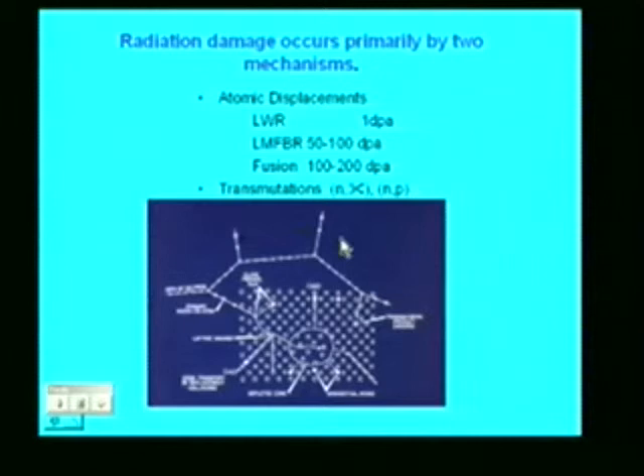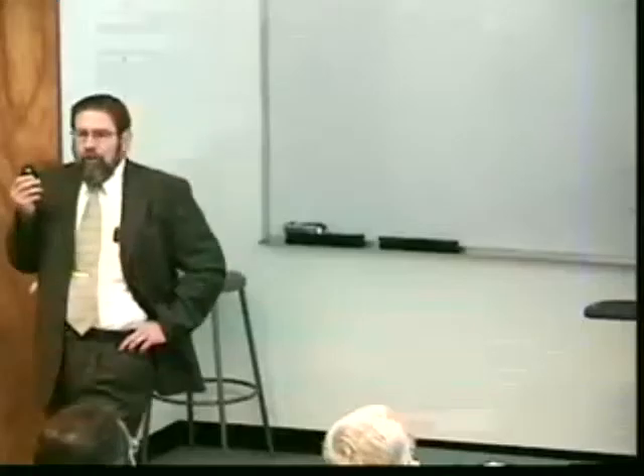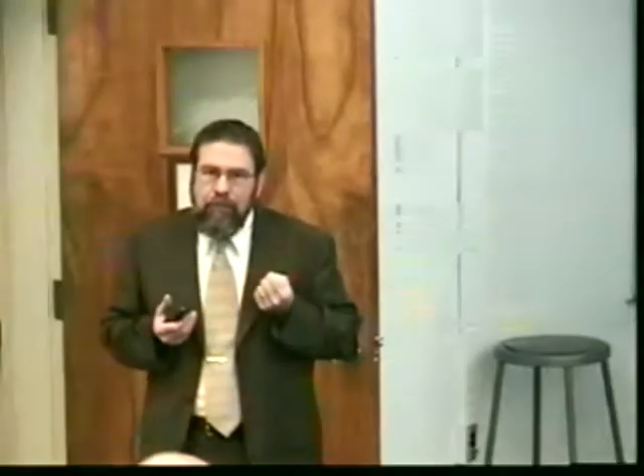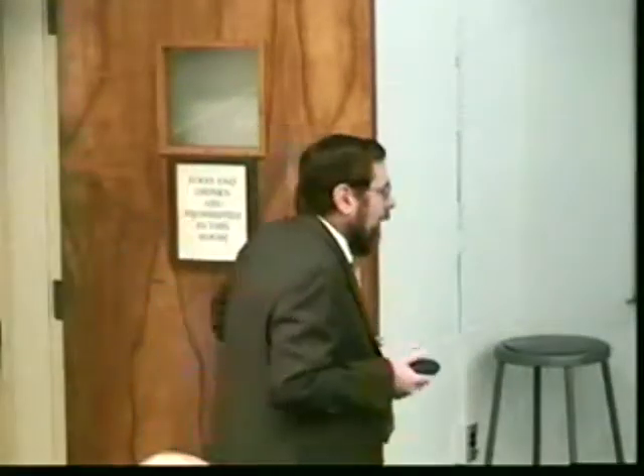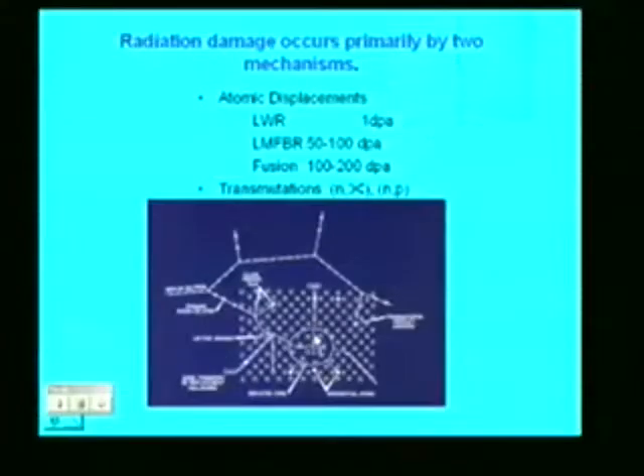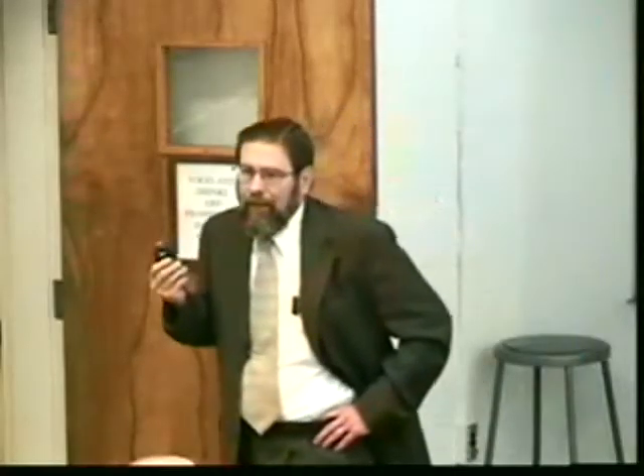So we get a cascading effect, and we said that they eject atoms from the lattice, so they produce an atom that's not in a lattice site, called an interstitial, squeezed in between, and where that atom came from is a vacancy. And at the core of that cascade, this diagram is showing we have something rich in vacancies, and then the interstitials usually are farther away. Just to put things in perspective, in an LWR, the materials may see about one displacement per atom. So that in a lifetime, on the average, every single atom in that structure has been displaced at least once.